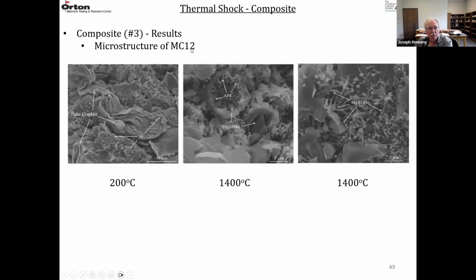And pretty much the same thing for MC12 at 200 and 1400 degrees C. You can see the flake graphite. There's some aluminum metallic spheres here. The aluminum nitride whiskers that have formed, the spinel that has formed, and this is just another micrograph of more spinel that's forming. These are identified with EDS, so with these features you can see the chemistry and identify what they are.